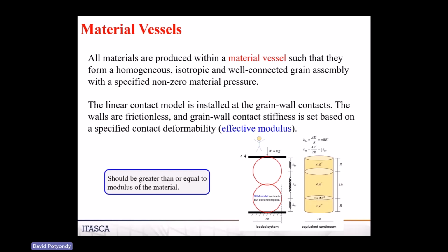Conversely, if the wall modulus is extremely high, you will not have overlaps. That's great. But you're going to have a very small time step, because remember, the time step is related to the stiffness in the system. If we have really high stiffness at that wall-particle interface, those springs are going to be vibrating really fast, so there has to be a really small time step. We don't want that. So what we want to do is tune down the effective modulus of the wall to be about equal to the modulus of the system. Whenever you're doing this, you have a target modulus for your material, so you know what this is.